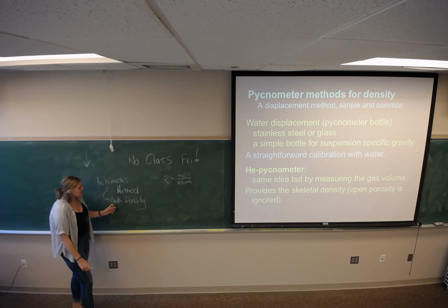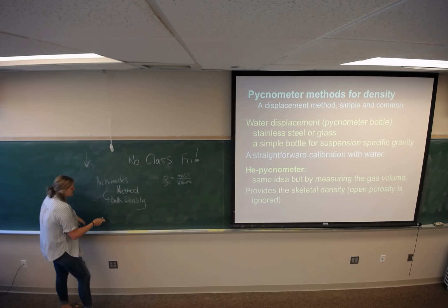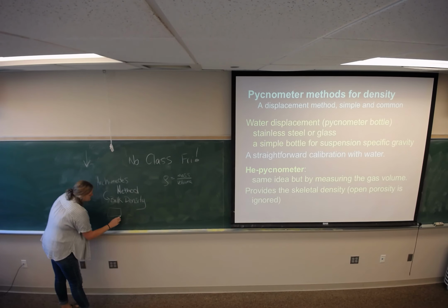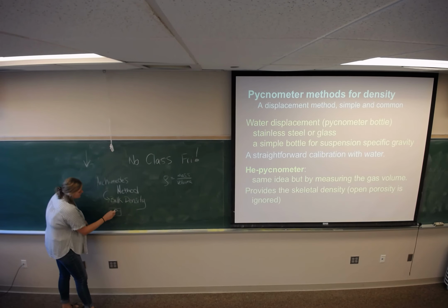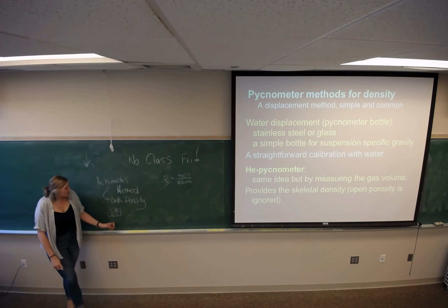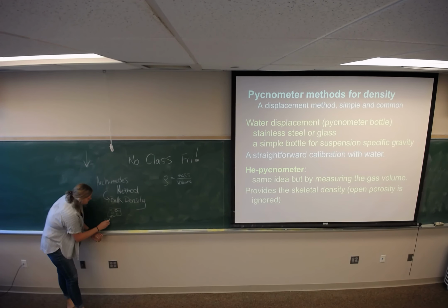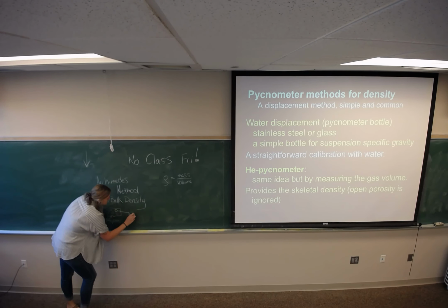A bulk density is, let's say you have some kind of ceramic compact that you've sintered, and it's not fully sintered, so it's not 100% dense. So you have open and closed pores. An open pore is going to be whenever part of the pore can be open to the surface or air getting in there. And then closed pores are when the pores are completely closed off from the outside of your material. This looks like Swiss cheese, but I think you get the gist. So these are called open pores. I don't know if you can read that. And then the ones that are closed, obviously, are called closed pores.